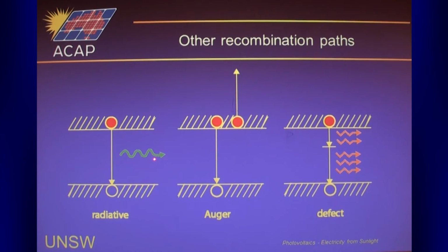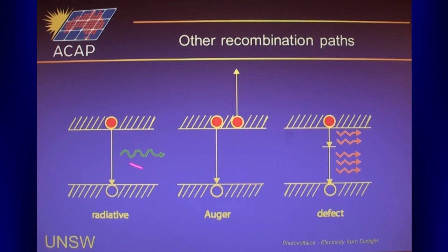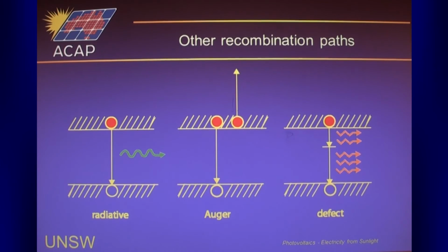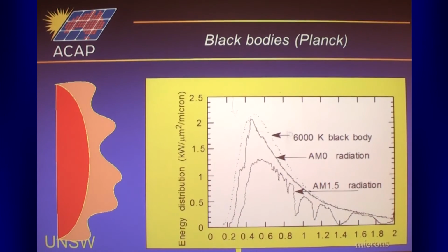This radiative process is quite interesting in that the extra energy of the electron that's released when the recombination event occurs causes a photon. And that photon has energy above the band gap of the material that it's occurring in, so it can be reabsorbed within the material somewhere else. In these other processes, you lose the carrier, you've lost it. In this process, the carrier lives on in the form of this photon. So the photon can bounce around in the device and it's not necessarily dead. But that makes it very complicated to analyze what's happening in the device, and people had struggled with that.